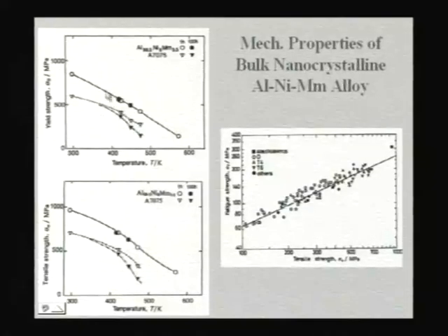So if you compare with a standard aluminum zinc magnesium alloy, you get a much higher strength in these alloys at any temperature of your consideration. So you can even talk in terms of up to around 600 Kelvin, and you get much higher strength. And similarly, look at the fatigue strength of this alloy and compare with any of the conventional alloys.